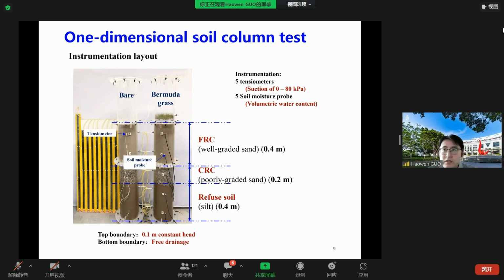The 1D test includes two soil columns. Each of them combines a 0.4 meter top FRC layer, a 0.2 meter CRC layer, and a 0.4 meter refuse soil layer. We also installed tensiometers and moisture probes to measure the soil suction and volumetric water content changes along the soil. At the top boundary of those two columns, we set a 0.1 meter constant water height for 8 hours to simulate a 16-year return period rainfall of Hong Kong. The bottom boundary was specified as free drainage.